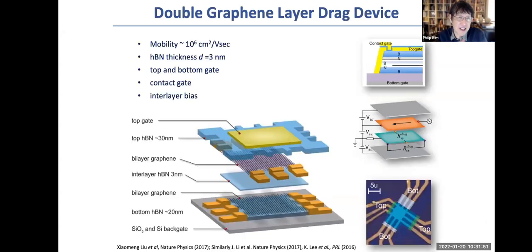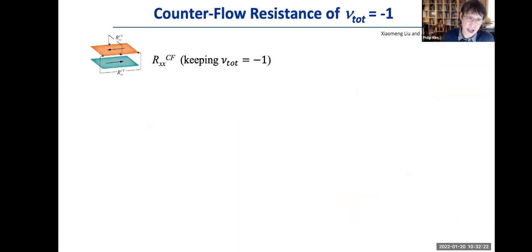So what we can do is, similar to that exciton condensation case, just copy that idea developed in semiconductor heterostructures, but simply replace them with 2D materials. In this particular case, we have two graphene layers separated by boron nitride, such that applying a magnetic field, both of the graphene layers start to develop Landau levels. We want to couple the electrons and holes in the partially filled Landau levels to form this magnetic exciton condensation state. And experimentally, we can measure this condensation state, as I said, by measuring the counterflow resistance, because if the magnetic excitons are condensed, we expect to see zero counterflow resistance. That's how the measurement is done here.